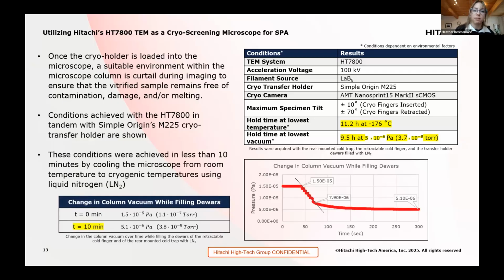And we're also able to achieve these conditions very quickly. In about 10 minutes, we're able to cool the microscope down from room temperature to cryogenic temperatures. I can show that data here with the change in the vacuum levels. So we're able to maintain this throughout the whole sample run and make sure that our environment within the microscope column is stable and secure for cryo observation.